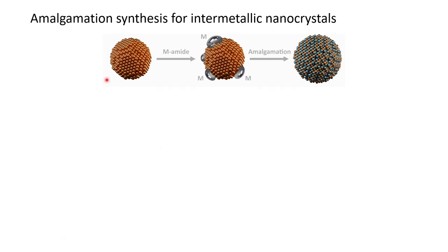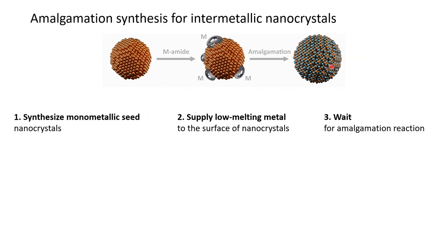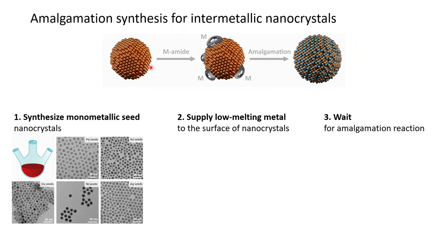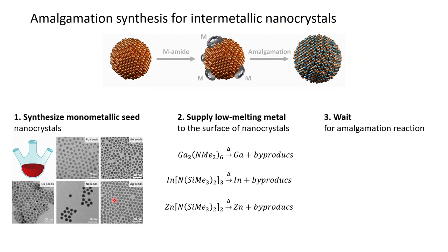So we use the so-called amalgamation synthesis. Amalgamation is the alloying between 2 metals, one of which is in the liquid form. Having one liquid metal is key for the synthesis, because the diffusivity of the liquid is much faster than the diffusivity of the solid, and so the liquid material creeps through the solid very fast and very homogeneously. Our synthesis is simple. It has 3 stages. The first stage is to synthesize monometallic seed nanocrystals, and here we are very thankful to all the people who were before us. They made so many monometallic seeds already, like palladium, gold, copper, nickel, and many more. So our task was to supply the low melting metal to the surface. And this is how we did it.